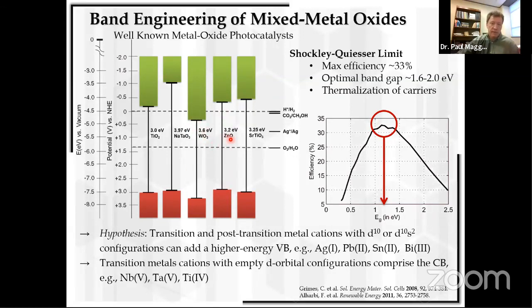For example, zinc oxide, strontium titanate, sodium tantalate. You notice that that conduction band edge varies a lot. It needs to stay above that proton reduction redox couple. So for example, tungsten trioxide falls just a little below it. But you can vary the early transition metal and vary that position.